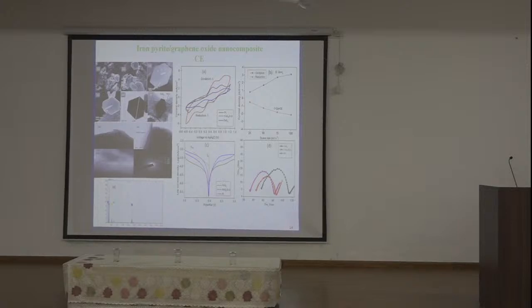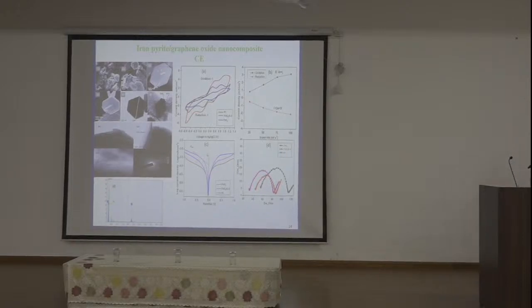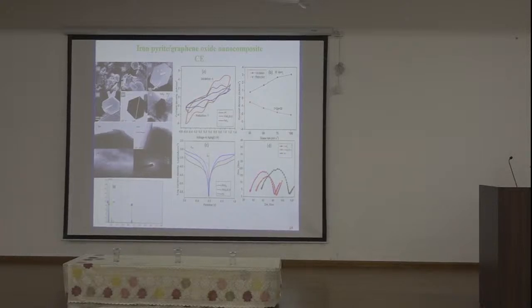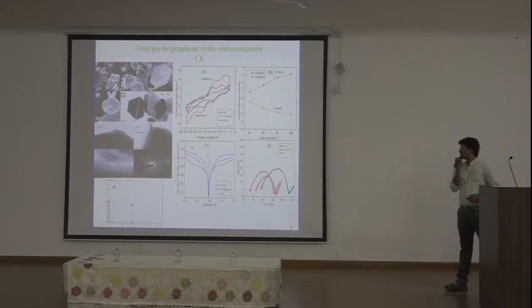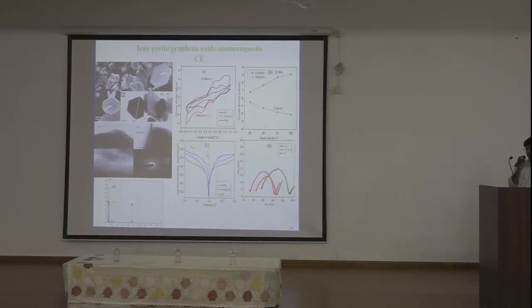And this is the Tafel polarization curve, also one of the techniques to see the limiting current density. The limiting current density is increasing with inclusion of RGO, and this slope indicates improved electrocatalytic activity. And also we can see the radius of the semicircle, as we already said, indicates the charge transfer resistance from the electrode to electrolyte. After inclusion of RGO, the charge transfer resistance is decreasing because of the high electrical conductivity in this RGO composite.